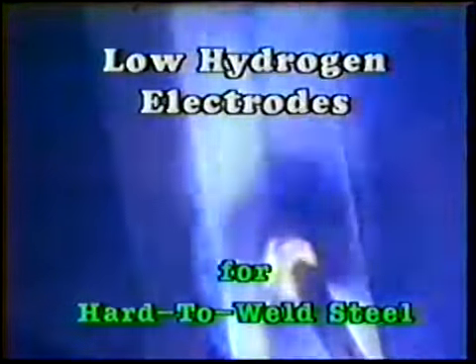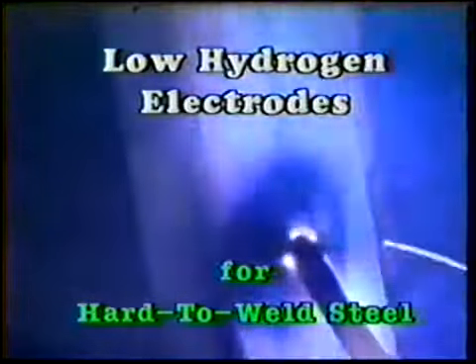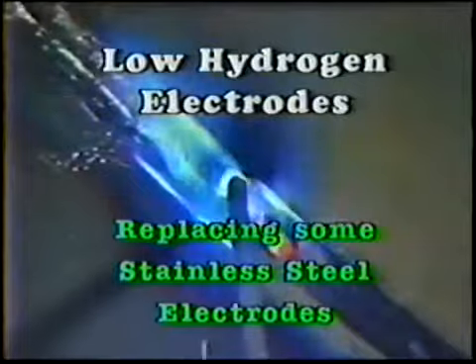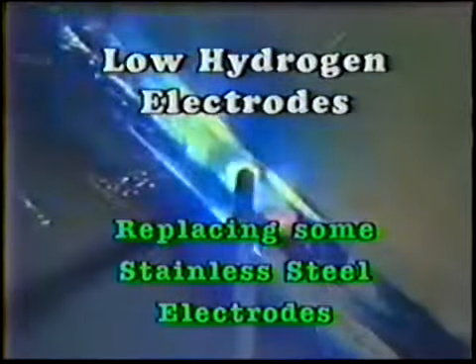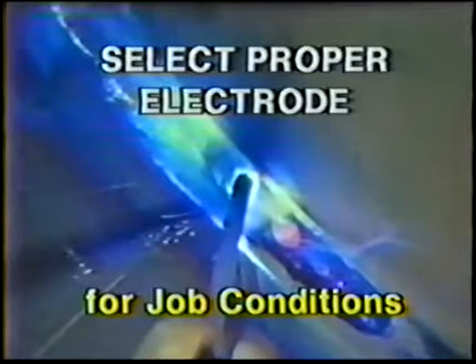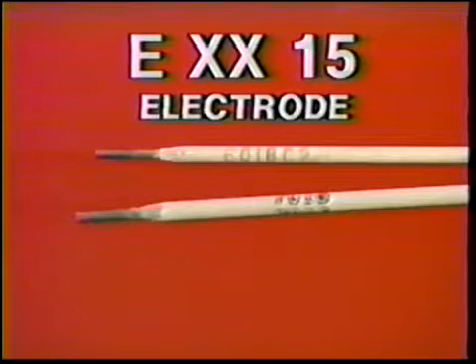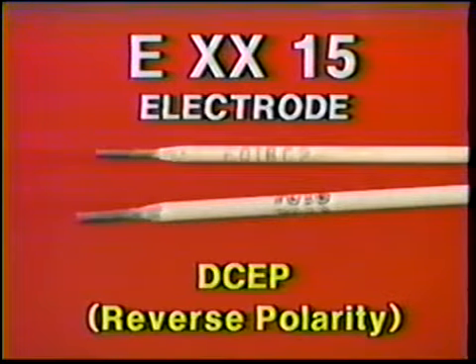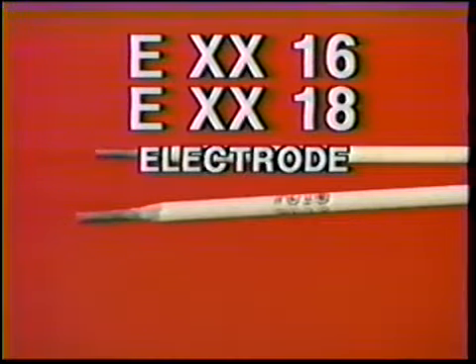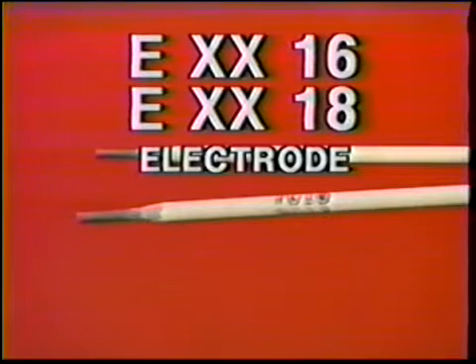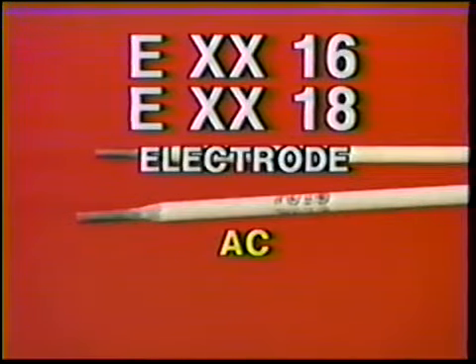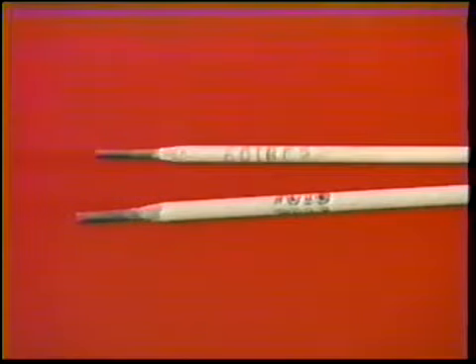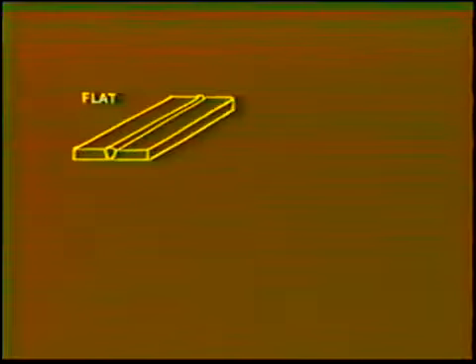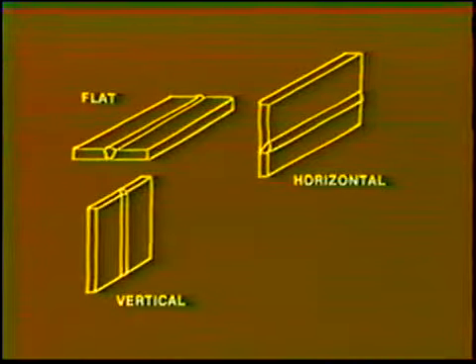Low hydrogen electrodes allow welding of metals that were previously considered hard to weld. They are replacing some plain carbon electrodes, and in some cases they are replacing stainless steel electrodes, which were often used for the hard-to-weld metals. When using low hydrogen electrodes, it is important to select the proper electrodes for the job condition. The EXX15 series electrode is used with direct current electrode positive. The EXX16 and 18 series electrodes are more popular and may be used with either alternating current or direct current electrode positive. These electrodes may be used in all positions: flat, horizontal, vertical, and overhead.